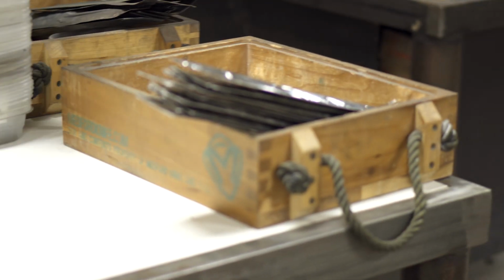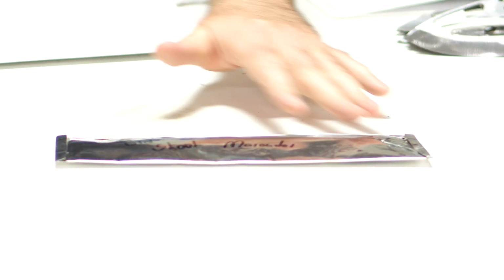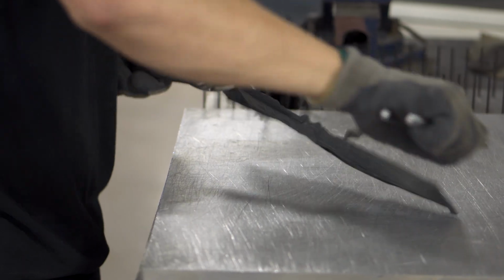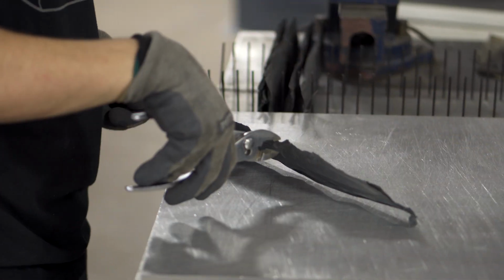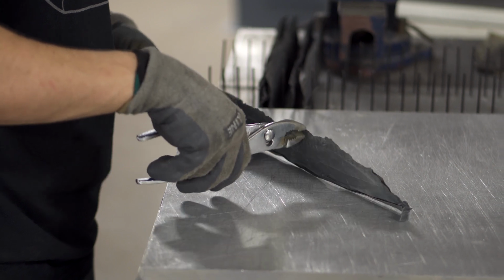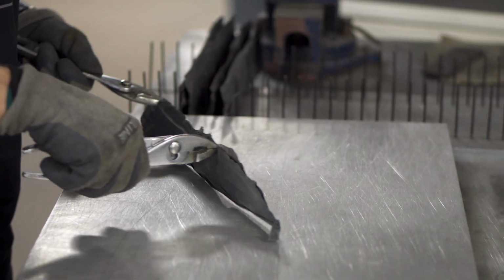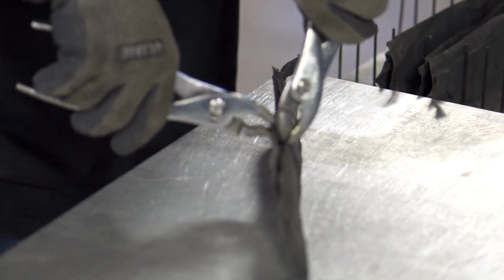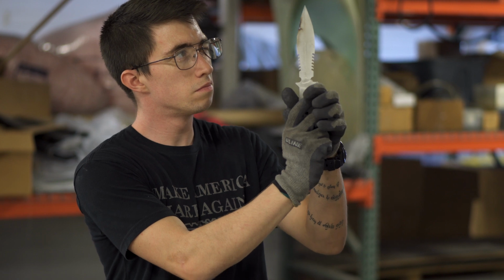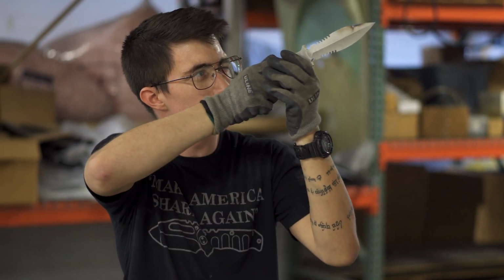We Inconel bag all of our stuff. So if you look over here, everything that goes through heat treating here gets put into an Inconel bag. It gets labeled what it is, what type of metal it is, and it gets heat treated in here. You use a little bit of stoichiometry and you know how much carbon to put inside to burn up the oxygen in the bag. And as it comes through 900 degrees Fahrenheit, it burns up that oxygen and you don't carburize your blades. Your blades come out a nice even gray color, and from there you can finish up your knife. If your blades coke up, carburize, scale, and get nasty looking,